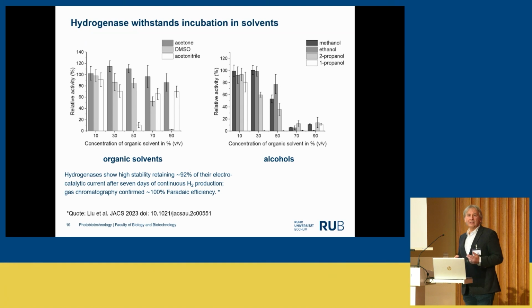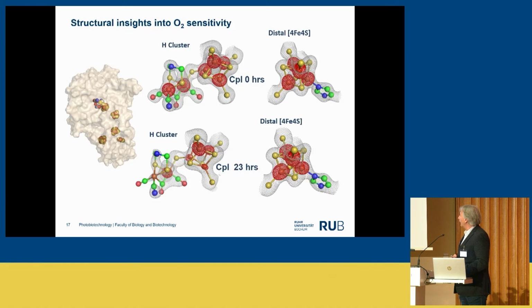The hydrogenases are also stable during production. Here is a study where, if you put the hydrogenase on an electrode, we recognize after 7 days that we still have the same activity as in the beginning. Okay, so we have a very stable enzyme against everything. We have only one little problem, that is oxygen. And we can analyze this very easily.